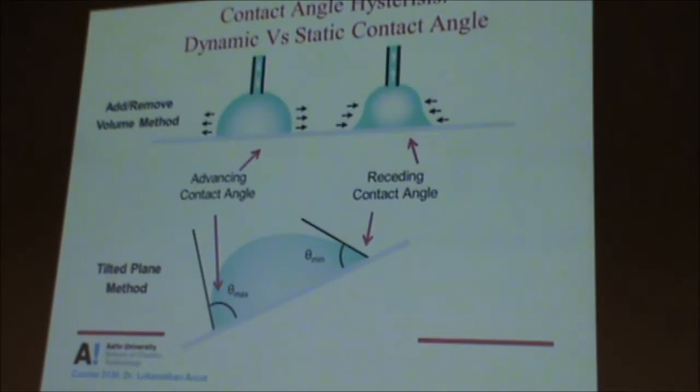Okay, so now, here is a syringe, you're either pushing the water or sucking the water. Let's say you're pushing water in. Now this region, because the surface is rough, the evaporation front or the solvent line gets pinned here, it gets stuck, buckled. So when you add more and more, instead of this moving here, because it is rough, it gets stuck there. So the drop expands like this. Okay, and so if you measure the contact angle, it's increasing.